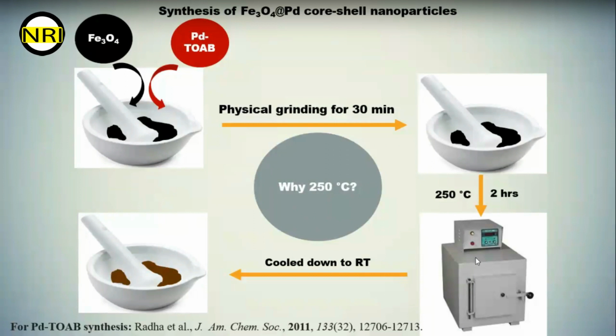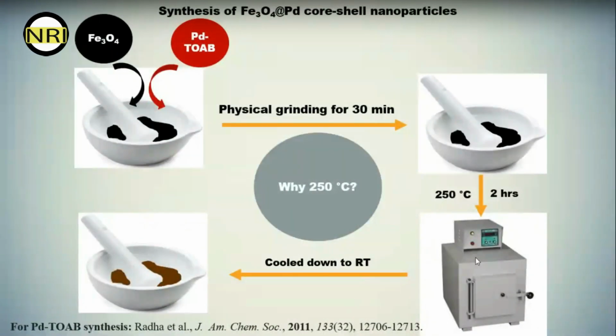This Pd-TOABr means palladium tetraoctylammonium bromide, which I have synthesized by following the literature published by Radha in JACS in 2011. But you can ask why I used 250 degrees C for this synthesis. To get the answer, I have to go to the next slide.